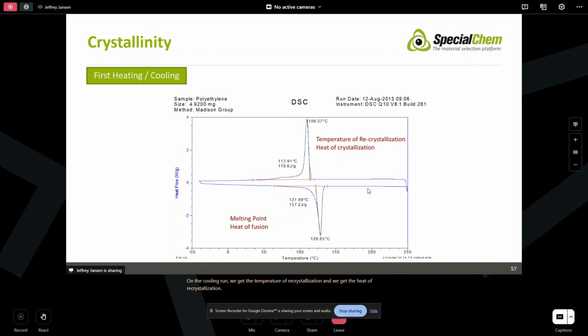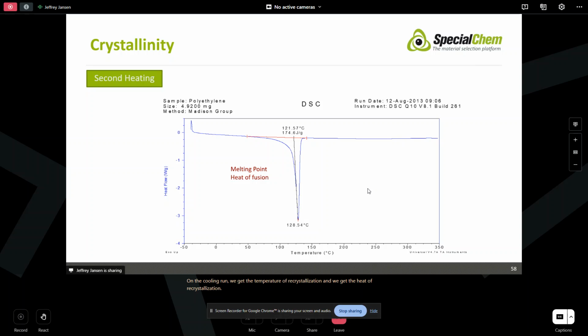Then we come back, again, as really part of the same run. We just plot them on two different plots typically. And we get the second heating run. And again, we're measuring the melting point and the heat of fusion of the material. This heat, cool, heat run in particular is going to allow us to assess the crystalline structure of the material, the crystallinity of the material as we received it, as opposed to how it wants to be. So let's see an example of that.